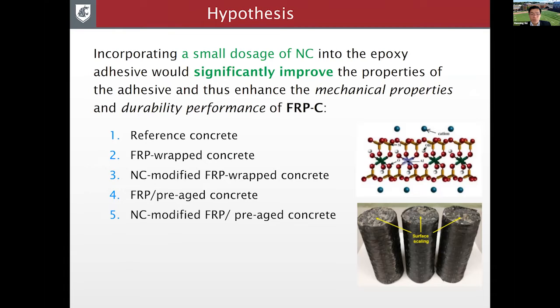So for that purpose, we fabricated 5 groups of concrete specimens or cylinders in the lab. One is reference concrete without any FRP. One is FRP-wrapped. The other one is nanoclay modified FRP-wrapped. And then the last 2 groups, we first age this concrete and then wrap it with FRP with or without nanoclay modification. So the idea is that the nanoclay modification not only would benefit the FRP used for new structures, but also for aged structures.